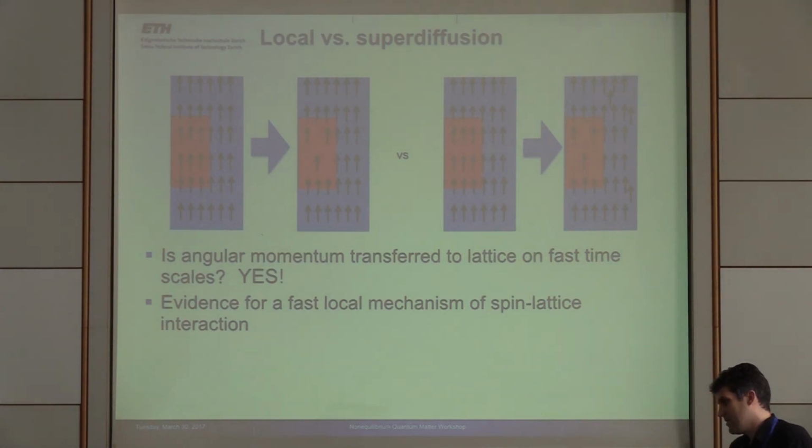That's an acoustic phonon, and you have a longitudinal and a transverse acoustic phonon. They travel at different speeds. The longitudinal one is subtracted out in our experiment because we do the subtraction of the two magnetization directions. So you only see the transverse wave. And that's modifying to some extent where the minima go. I got it. Yeah, thanks.